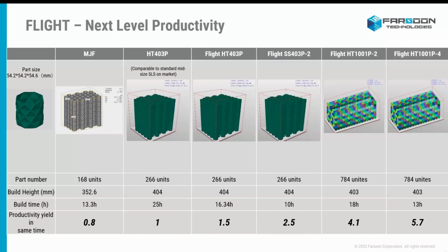Moving to our dual laser fiber system, we can see that we can cut down that build time even further to a mere 10 hours, giving us 2.5 times the productivity yield. That's 266 parts in 10 hours compared to 168 parts in 13 hours.